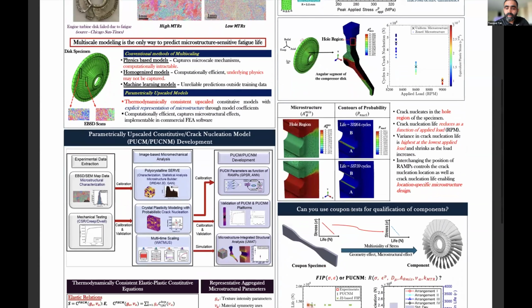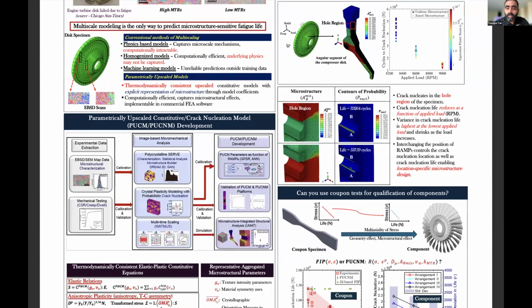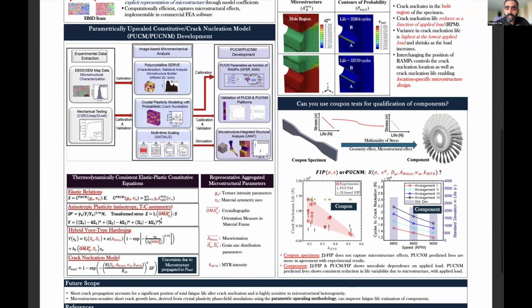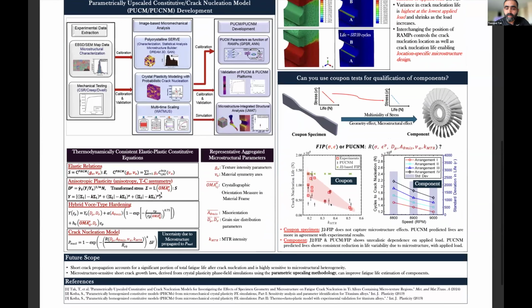So the ultimate objective was to validate this model with experiments. We have some experimental results where we know the underlying microstructure from EBSD scans. We quantify that, and then we assign that microstructure to our parametrically upscaled model, and we compare our fatigue crack nucleation predictions as a function of the MTR intensity. In general, we see a continuous decrease in life as a function of the MTR intensity.